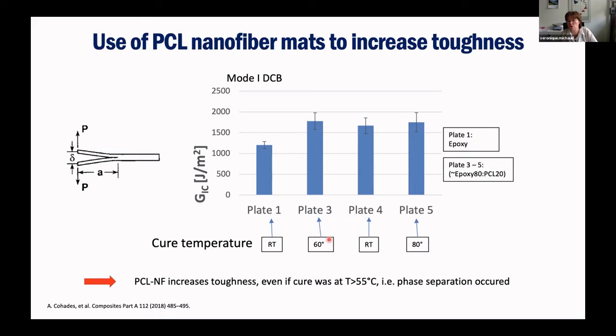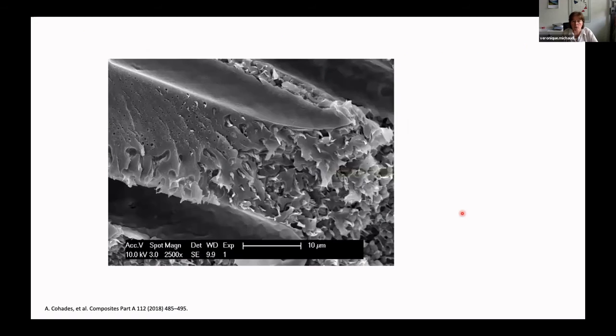But then we also cured some plates at 60 and 80 degrees to see what happens if we actually melt. So we go over the melting temperature of the PCL. We should have a melting and a phase separation. And we saw that indeed we still had a very good toughness. So it works well. We looked at the microstructure, and this is an example of what it looks like.